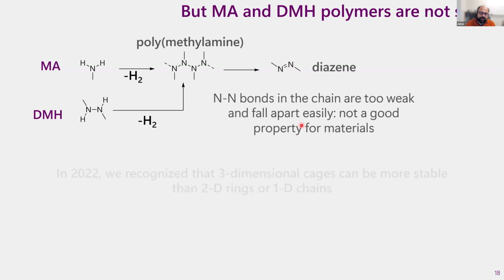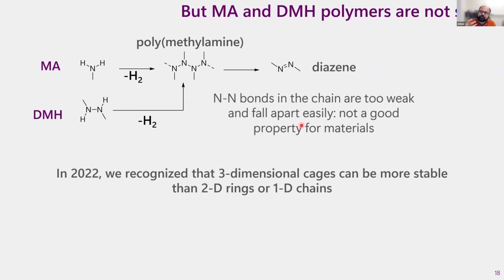And this is where our discovery comes in because we recognized in 2022 that if you put nitrogen into three-dimensional structures instead of two-dimensional or one-dimensional structures, then it becomes a lot more stable. As an analogy, you can take a piece of paper and tear off a small strip of that paper. Okay? That small strip of paper is kind of like a one-dimensional string. Now, if you have a very thin strip of paper, you can flex it and bend it in many different ways. And it turns out that this flexibility ultimately makes the polymer a little bit less stable because it can achieve configurations that are explosive. Not good for materials. So if you do this with nitrogen, one-dimensional chains, that's no good.